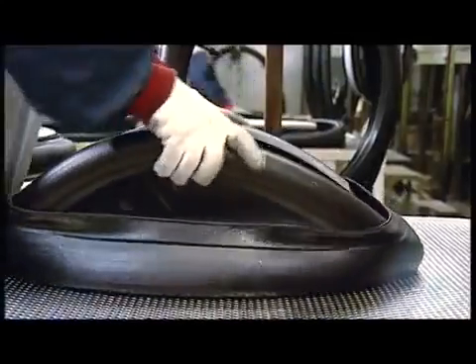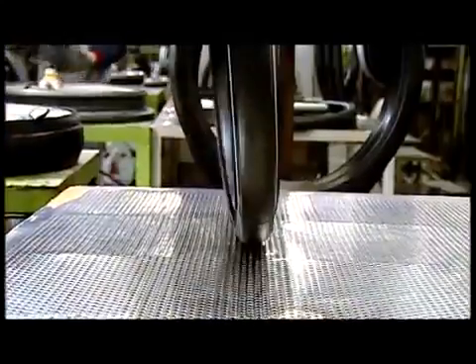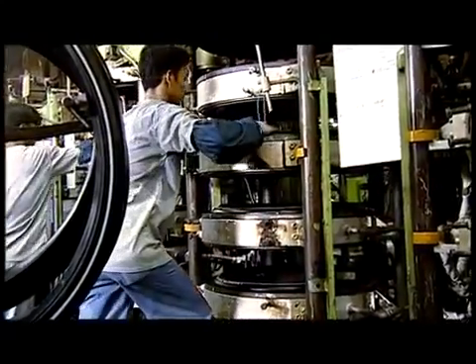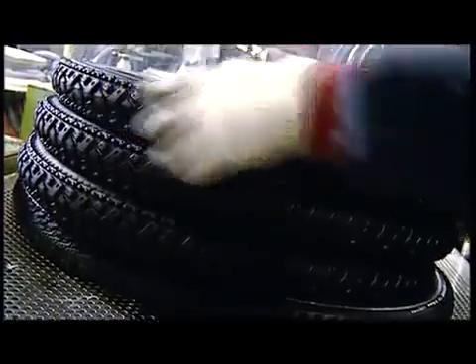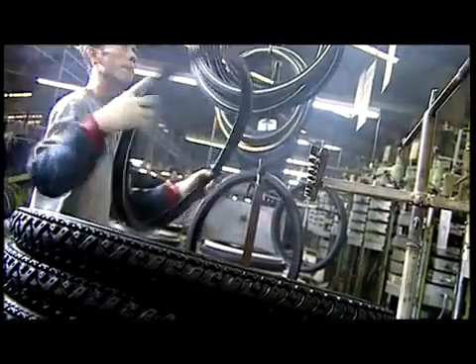At this point, the chemical process of vulcanization takes place that will transform it. But first, a heating tube is inserted inside the raw tire. Finally, it is ready to be vulcanized in the tire press — like a giant waffle iron at around 170 degrees for five to six minutes. After each cycle, six tires with their special Schwalbe treads are born. As the tire now has its flexible characteristics, only after vulcanization is it possible to describe it as rubber.